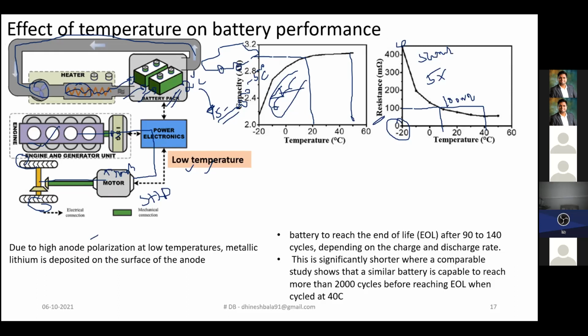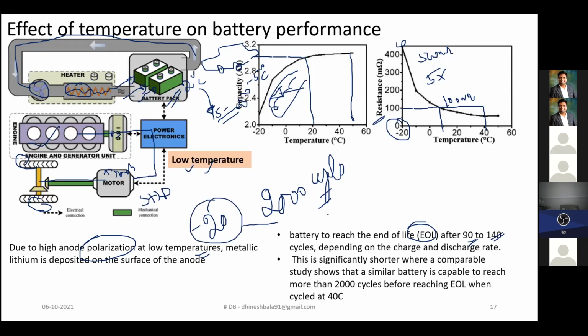So due to high anode polarization at the low temperature condition, metallic lithium would be deposited on the surface of the anode. What actually results is an impact on the cyclic life of your lithium ion batteries. The battery would reach its end of life after even 90 to 140 cycles. Normally it will range up to 2000 cycles for a normal lithium ion battery, but if you are trying to charge your battery at the temperature limit of minus 20 degrees Celsius, you will reach your end of life in merely 90 to 140 cycles.